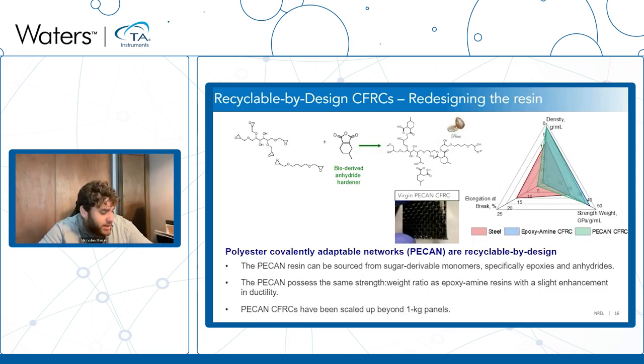And by what we've done, I mean the people who work in the lab, such as Eric, have done throughout their work. So at NREL, we've taken this bio-derived mixture of a sorbitol polyglycidyl ether, a butanediol diglycidyl ether, and this anhydride-based monomer, which can come from multiple bio-derived constituents, such as isoprene and maleic anhydride, to look specifically at how we can do this. And can we make a CFRC?